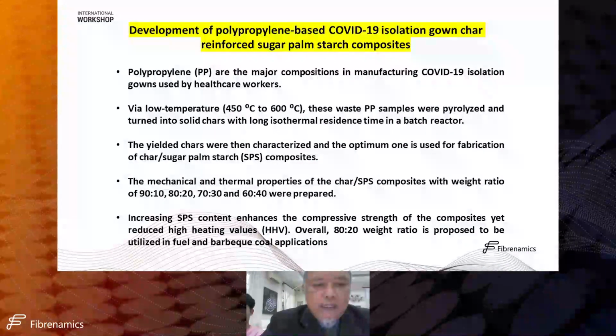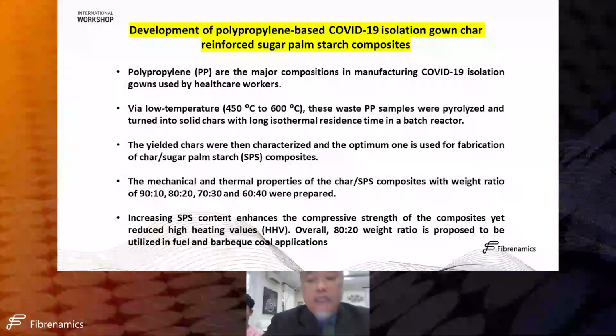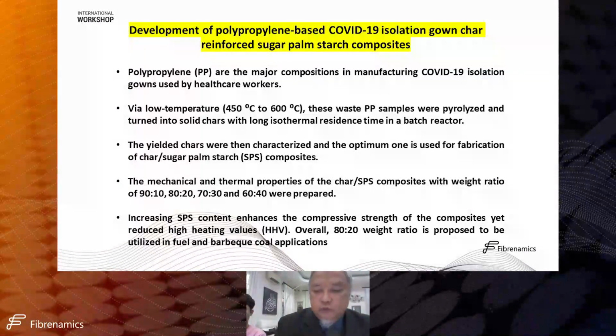The main result is that increasing the starch, the biopolymer content, enhances the compressive strength of the composite, yet reduces the high heating value. So we found that an 80-20 weight ratio is proposed to be utilized in fuel and barbecue coal application, meaning that in terms of compressive strength, adding the biopolymer is a positive move. That's why we believe that biocomposite can contribute during COVID-19.